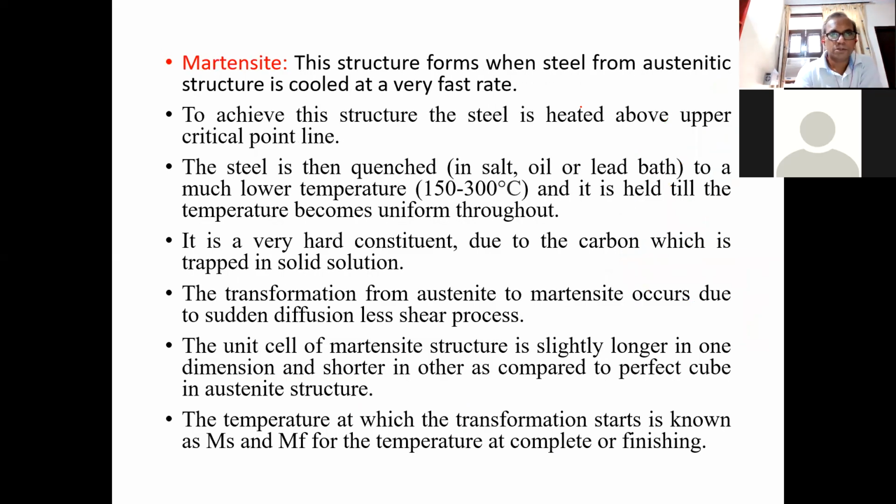And what is this? What they said is that the steel is quenched in a salt, oil or lead bath to a much lower temperature, around 150 degrees centigrade to 300 degrees centigrade, and it is held till the temperature becomes uniform. It's important.